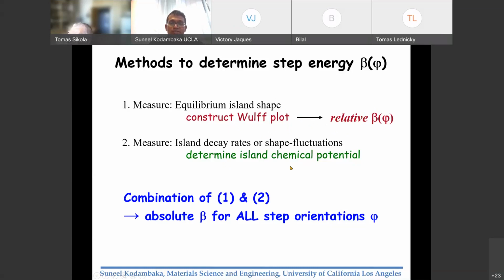We're going to do two things. One is to use the island disappearance rates that I just mentioned, the Ostwald ripening phenomena. The other way is to measure the fluctuations in the island shapes that you observe during the island decay process, and use either of them to determine the island chemical potential. Once you have this, we have absolute step energies as a function of step orientation.